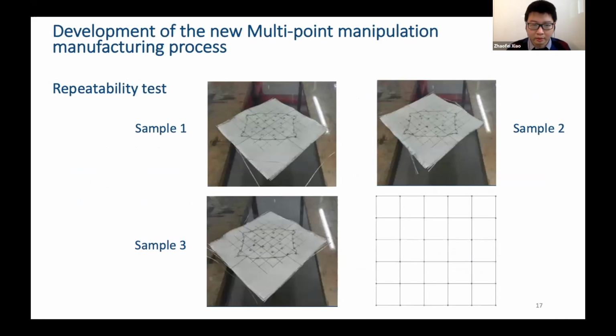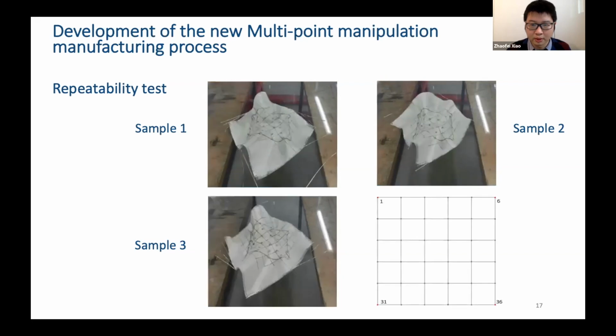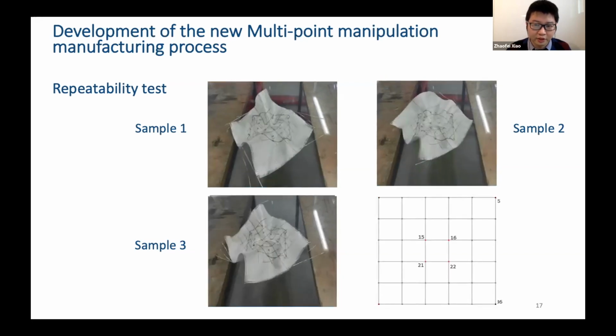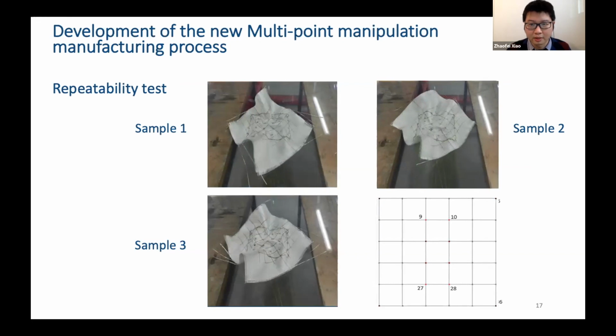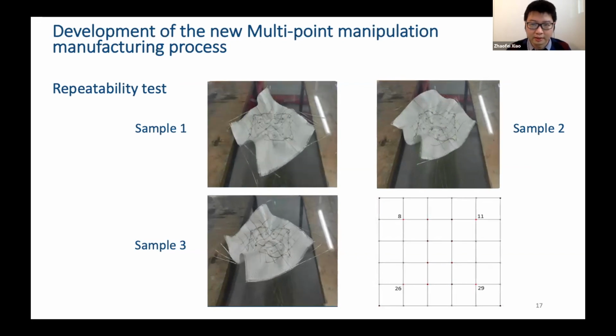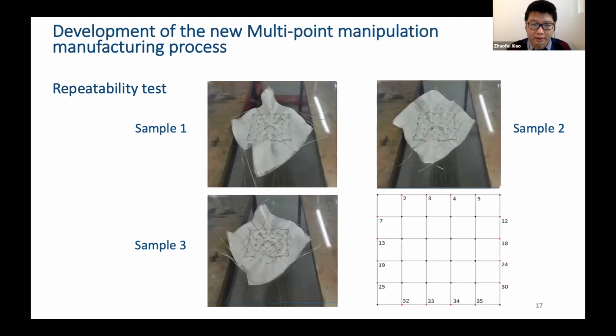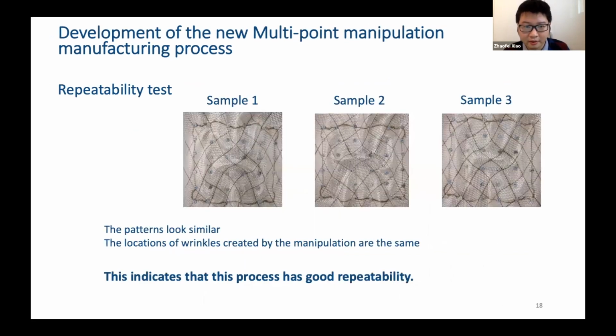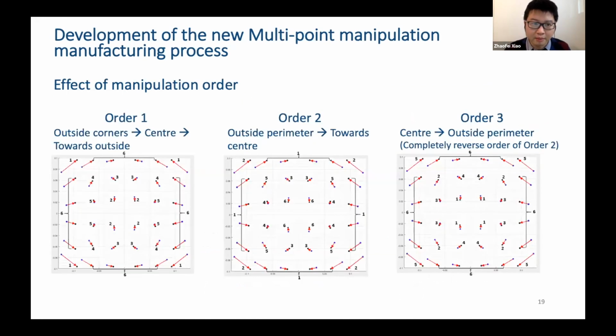If we go through the repeatability test from 3 samples, you can see at each manipulation step, the fabric has a similar shape. If I go through the whole process and compare their final steered pattern, we see they are quite similar, and the locations of the wrinkles created by the manipulation are also the same. So it indicates this process has good repeatability. The next step is to understand the effect of manipulation order.